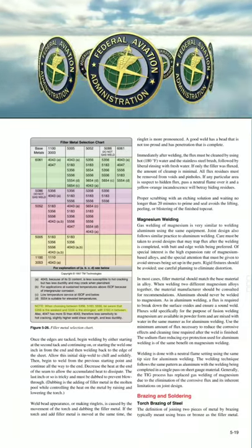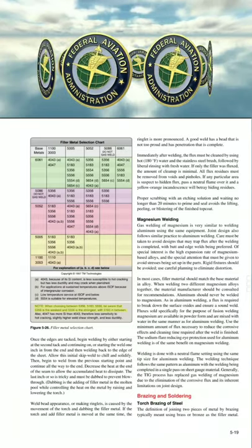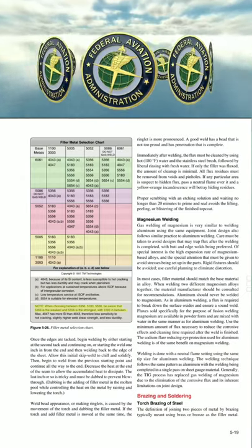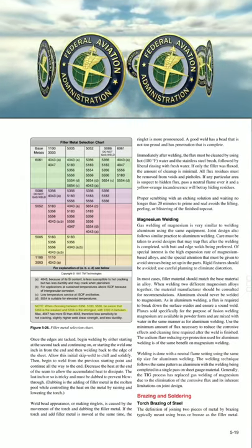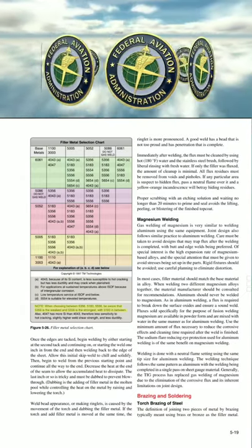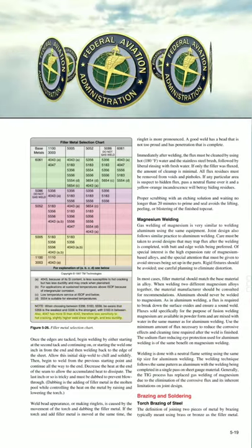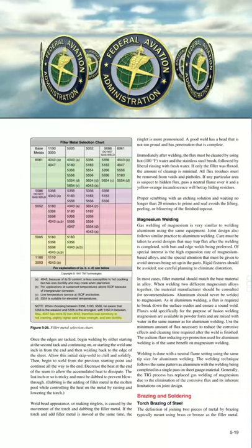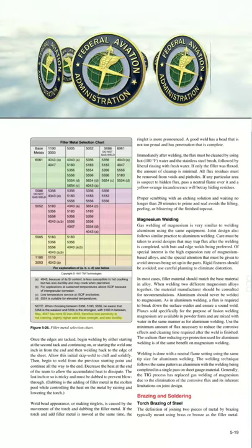Note, when choosing between 5356, 5183, and 5556, be aware that 5356 is the weakest and 5556 is the strongest, with 5183 in between. Also, 4047 has more silicon than 4043, therefore less sensitivity to hot cracking, slightly higher weld shear strength, and less ductility.